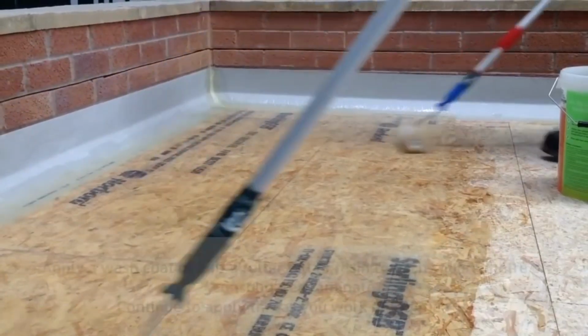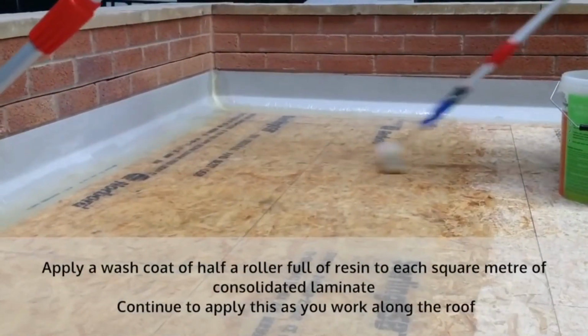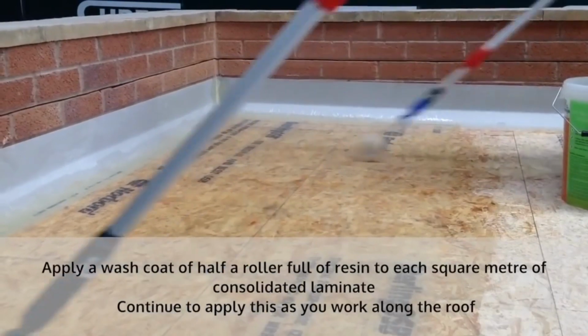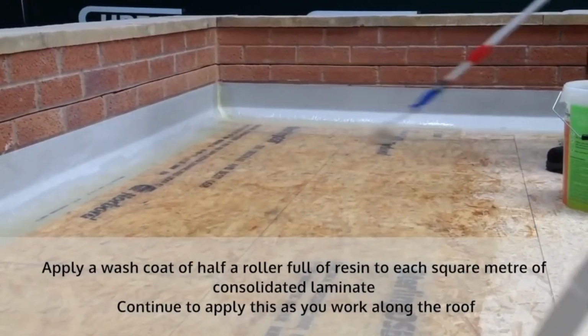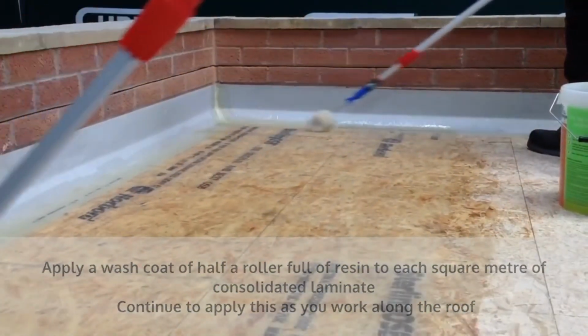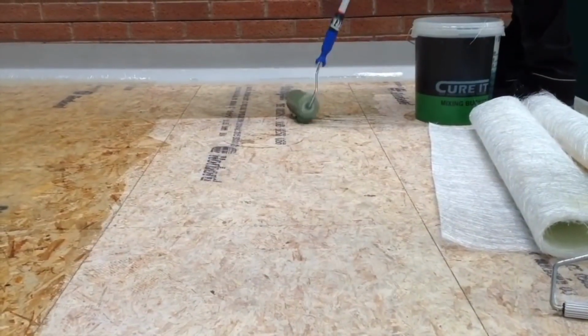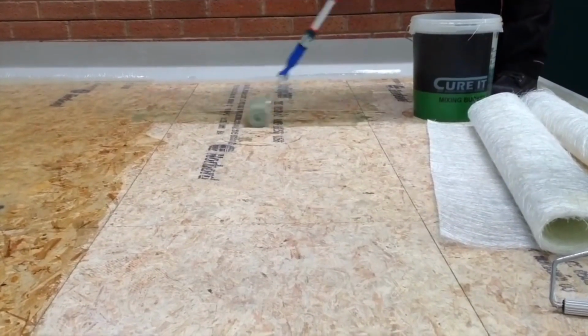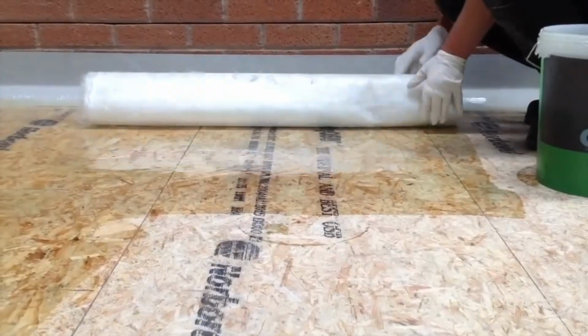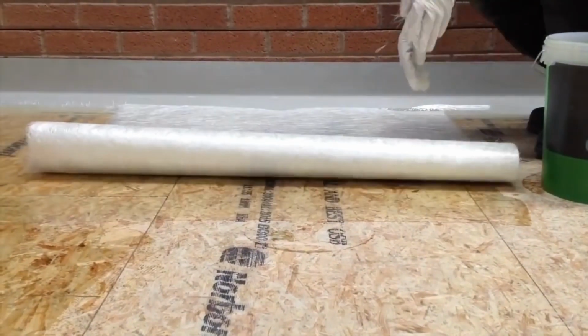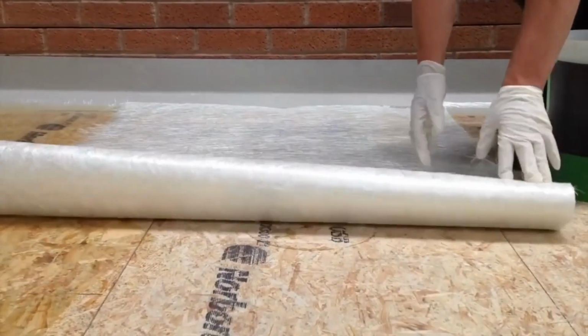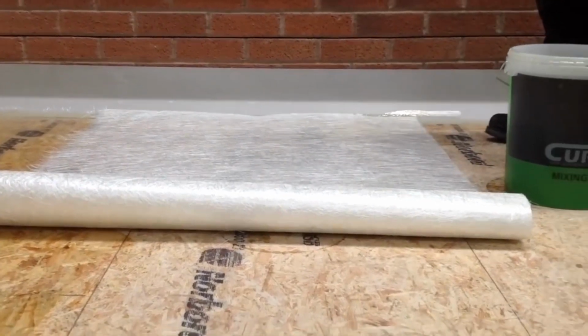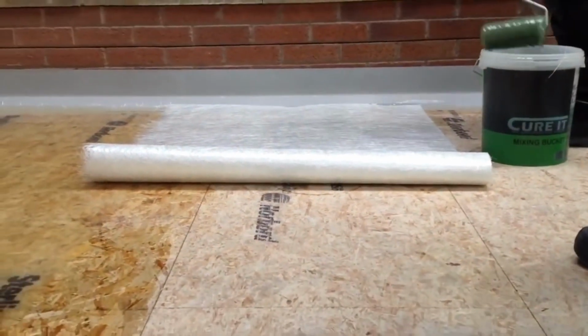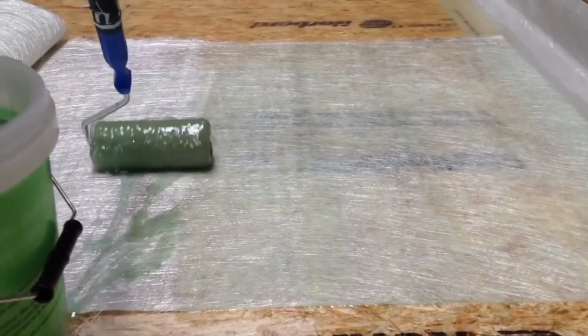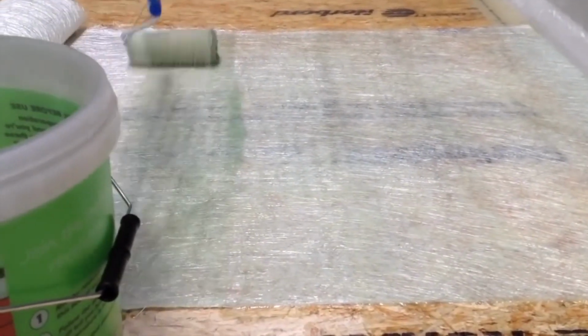Before wetting out the first square meter of the second row, go back to the paddle-rolled first square meter and apply a wash coat of half a roller full of resin. After applying a wash coat to the first square meter, start on the next run. Remember that each subsequent run should overlap the last by 50 mm, ensuring that the feathered edge is laid over the square edge, and repeat the laminate process. Work along the entire roof in rows until the entire roof deck is complete.